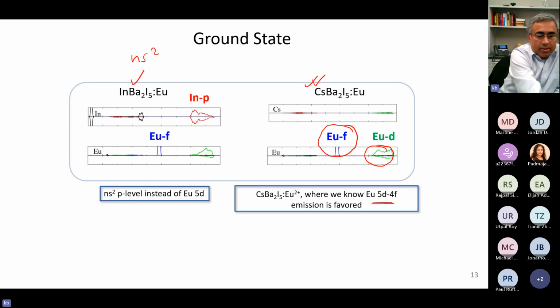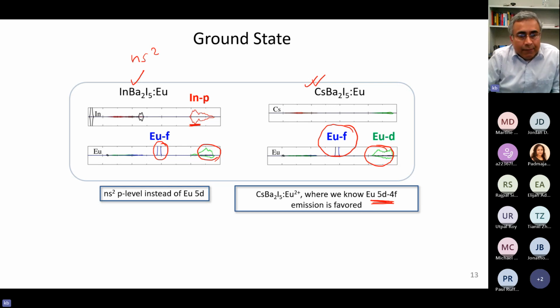However, in these Ns2 compounds, we have some problem. The bottom of the conduction band has indium P character, not europium D character. If you dope indium barium iodide with europium, you will have europium F in the middle of the gap. However, europium D will end up near the top of the conduction band, not the bottom of the conduction band. The bottom of the conduction band has indium P character. That is going to be a problem if you are looking for D-F transition. You won't have that transition. So that's why we concluded that europium may not be a very efficient activator in case of our Ns2 compounds. That's okay. So europium is not an activator. We could look for other activators that could work well for these compounds, or we can look for self-activation.